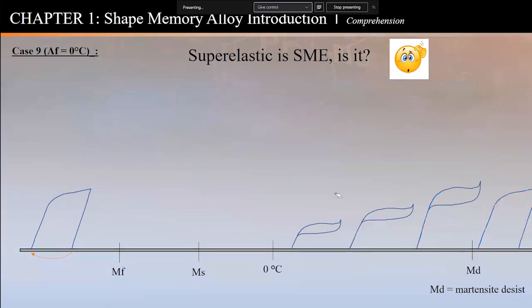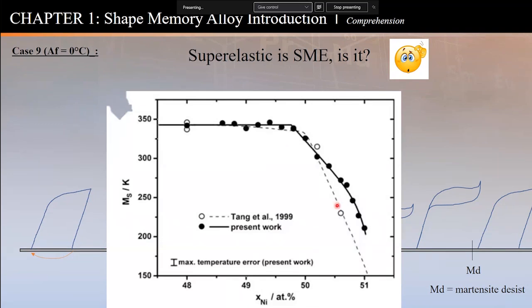And this goes into the material science part of things. If I take nickel and titanium that I mentioned before, and I do this atomic, if I add nickel or remove nickel, 50-50 is here, for example, 50% nickel. I take 5 grams of titanium and 5 grams of nickel, I mix them together, and that shape memory alloy gives me a transformation temperature MS, that stands for martensite start, of say 340, whatever that is, Kelvin, for example. Okay, I'm here. But let's say I need to change where the material is activated. I need to activate down here. What we do, we simply add nickel, more nickel. Now my MS is down here, 250.